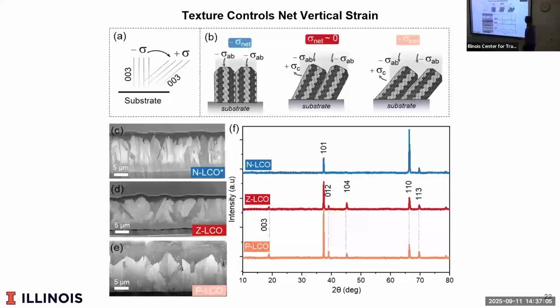So what are the details? Well, if you have this crystal that's swelling and expanding, you can actually control the angles of the crystal, because if this side is expanding, this side's contracting. If you go to the right angle, then it won't do anything. It'll stay the same. If you control the orientation of the crystal, it would be like making a material that has no thermal expansion coefficient. So, you can make materials that in one direction have no CTE. It might mean in a different direction they expand and contract a lot with temperature.